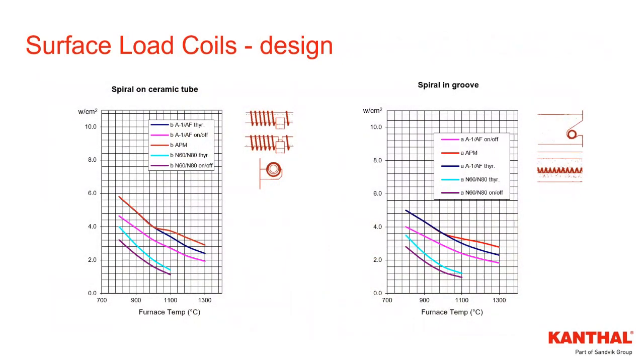I wanted to include some graphs to demonstrate there are differences for recommendations when designing heating elements based on the style of heating element and how it's used within a furnace. So this is all part of the heating element selection process. The two graphs here just show some comparative information on a coiled element and its resulting watt loading. So it's basically its power output, and comparing a coiled element that's freely radiating, so it's supported on a ceramic tube that spans the furnace chamber, and then another different type of coil heating element that's installed within grooves that's contained within the insulation walls in a furnace. So we consider that like a semi-embedded heating element. And you can see in the graphs that there's different watt loading recommendations depending on what style or alloy that's used. So it's a nickel chrome or an iron chrome aluminum, and the different ways that the elements are installed.